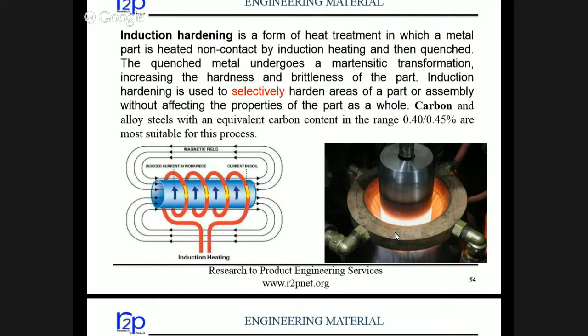But the advantage is also there. The controls in case carburizing are much better, and wherever we need to do the hardening of the whole component, like in a gear or a shaft, then we go for case carburizing, and if only selective portions are to be hardened, then we go for induction hardening. So in a way, this is a faster and cost-effective process. Induction hardening is to be done on carbon steels having carbon in the range 0.4 to 0.45%. So carbon is already required to be there because we are not adding it. In case of carburizing, we first add carbon, then do the quenching. Here carbon is already there.